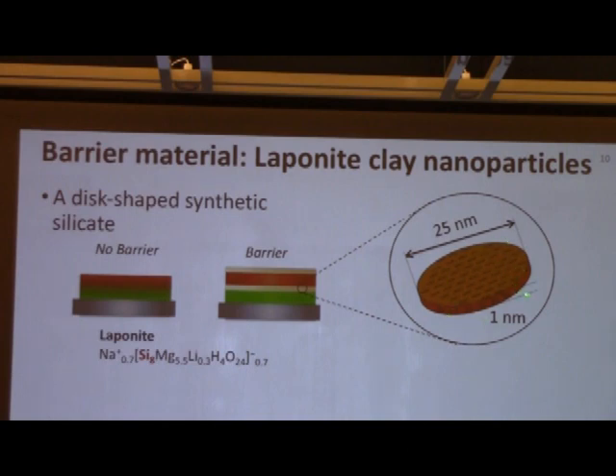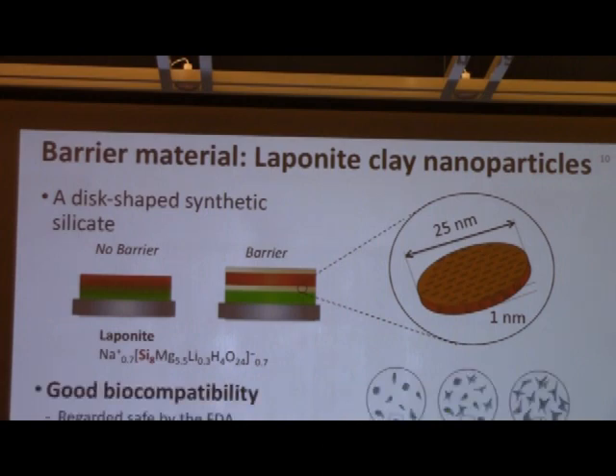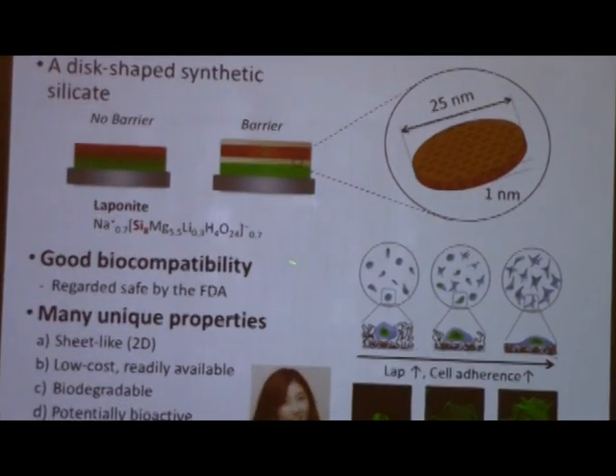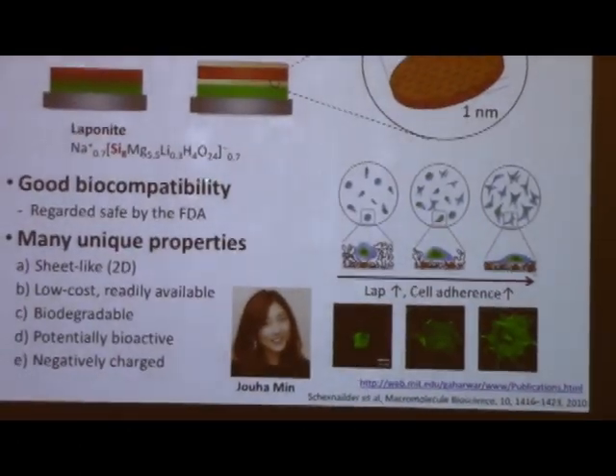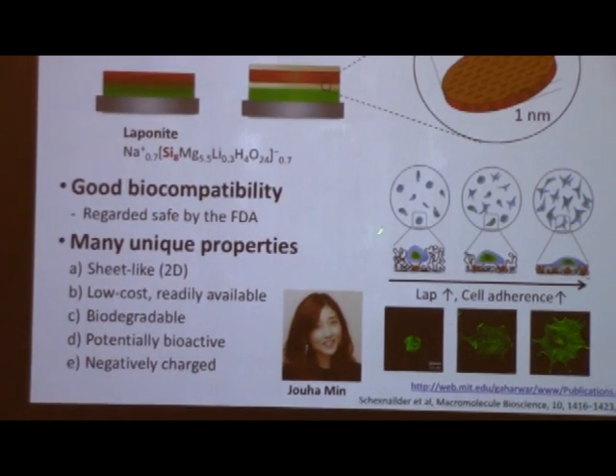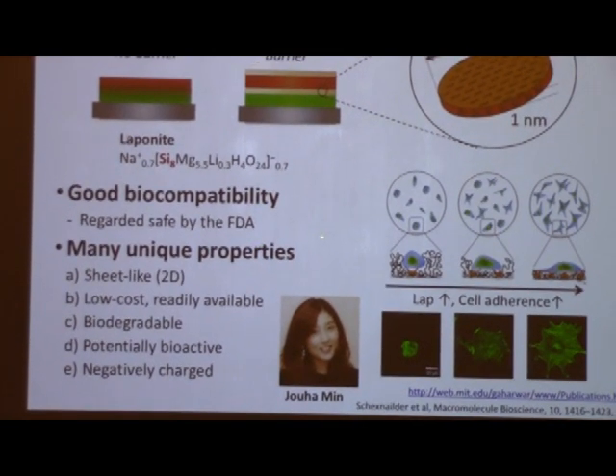It's actually a silicate, just common silica, but it's in this clay form in which you have a disc shape, just a nanometer in thickness, anywhere from 25 to a few hundred nanometers in diameter. And these negatively charged clay discs will adsorb very nicely from water as we build up a film. It turns out that there are a whole range of laponite clays that are out there, as well as montmorillonite and other clays. A number of them are regarded as safe by the FDA and have good biocompatibility and interact well with cells and even enable cell adhesion.